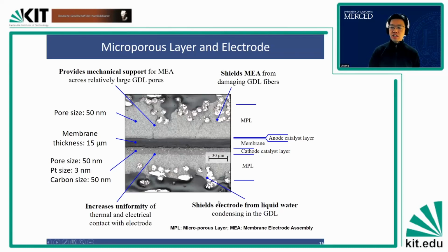Last but not least is shielding the electrode from liquid water. As I mentioned earlier, this microporous layer, on the top and bottom, both have a strong hydrophobic agent, PTFE, so this layer is very hydrophobic. When you have water generated and potentially condensed, water will then be pushed out through these large pores rather than these small hydrophobic pores. And so we developed a lot of different materials and different tools to characterize and study this microporous layer and electrode.